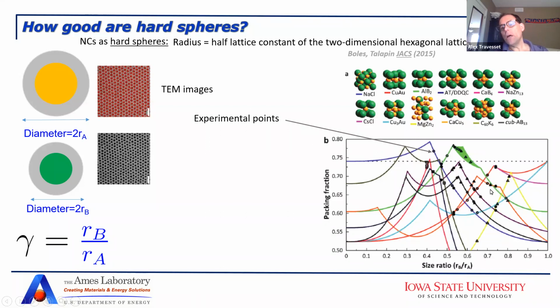It tells you that when you have a superlattice, you do these plots, and if the superlattice exists, it should happen around the maximum of the packing fraction. But when you look at this more closely, you start realizing that the correlation is not so great. First of all, magnesium zinc 2 has a packing fraction smaller than the single component. So the first question is, if we are taking this seriously, why doesn't this system phase separate into different FCC lattices, one for each type of nanoparticle, which would give you a higher packing fraction? That's question number 1.